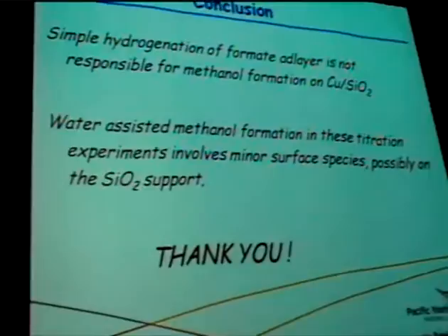But it's still alive. What's true is that the simple hydrogenation of a formate by the majority hydrogen adsorbed on copper is not responsible for making the methanol. And the water-assisted methanol formation in these experiments undoubtedly involves some minor species that we can't measure, and they could even be on the support. So we're trying to do this one. It's hard to get IR through unsupported copper, but that's what we're trying to do now. So with that, I'm out of time. Thank you for listening.